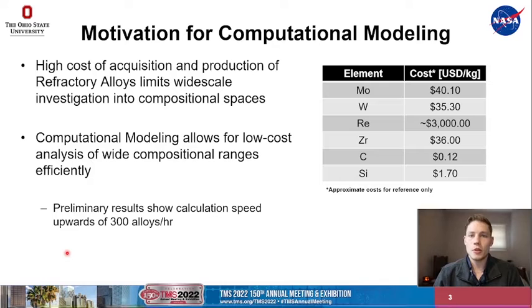We have preliminary results of some of the programs we've been writing where we are calculating around 300 alloys per hour. This speed allows us to brute force calculations over a wide compositional range and analyze all the material properties for each of those compositions. This allows us to really tailor the elements and the ratio of all the elements that are going into these alloys in order to get the best material properties.